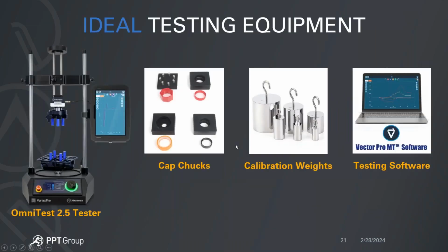So, the ideal equipment for a CRC test, again, apologize for the spelling there, is our Vortex Pro tester, which essentially allows an operator to configure a test that runs at a preset rotational speed, runs to a preset testing angle, and then measures what that release torque value is. At the same time, we have calibrated weights that we apply on the top to simulate the actual axial force needed to engage the release mechanism to get it to open. So if you do this the first time, it allows you to test different samples regardless of operator, regardless of the testing environment, over and over again.